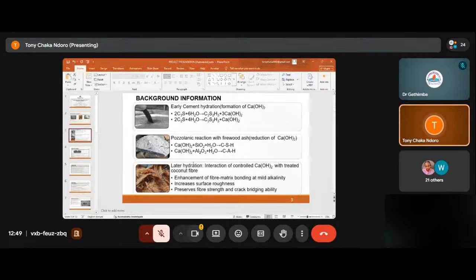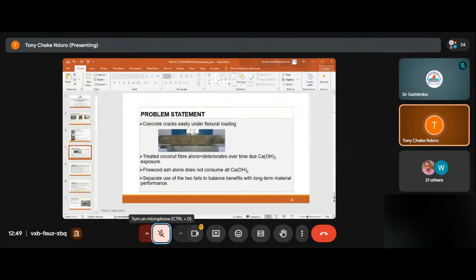It will be left, but in little amounts, in which it will interact with the treated coconut fiber, which will lead to the enhancement of fiber matrix bonding at mild alkalinity and increase surface roughness, and also preserve the fiber strength and crack bridge ability. The problem statement: the concrete cracks under the flexural loading, and the treated coconut fiber will deteriorate over time due to the excess calcium hydroxide. The firewood ash alone does not consume all the calcium hydroxide, and the separate use of the two will fail to balance the benefits of the long-term material performance of the concrete.